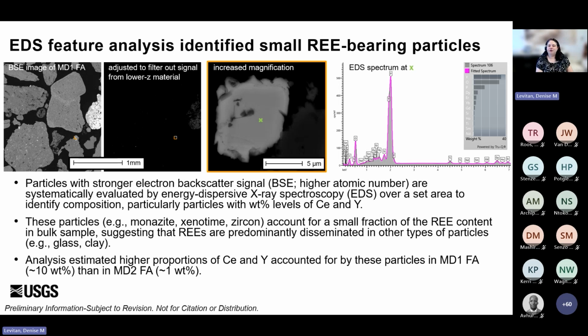So if we zoom in on this little square, this is a 1 millimeter scale bar for these two images, and this is 5 microns for that tiny little square there. We see this bright particle here at increased magnification, and then if we hit it with the EDS, we can get a chemical spectrum. It's difficult to see the labels here, but what this spectrum shows is that this mineral is rich in yttrium and phosphorus. So we can then infer that it's likely the rare earth element mineral xenotime, or yttrium phosphate.